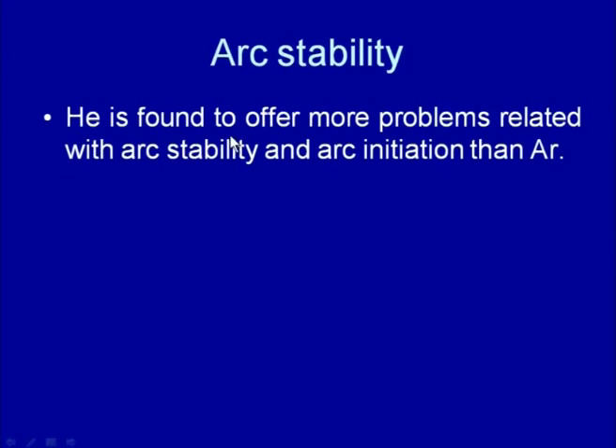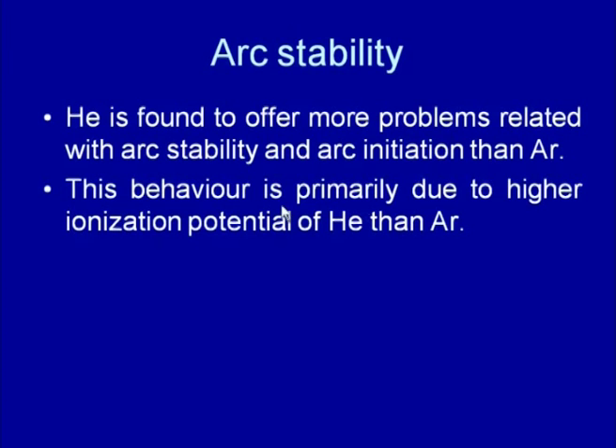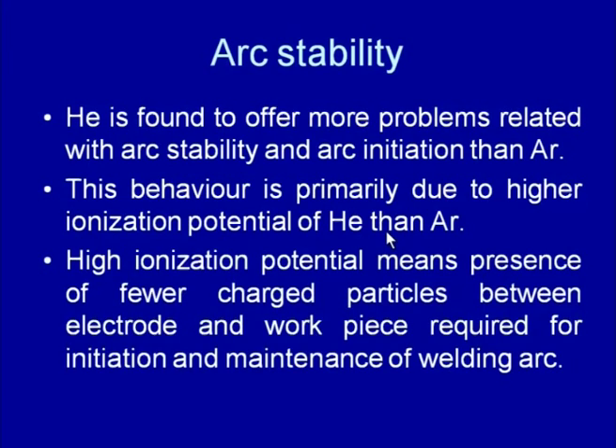Further, the selection of the shielding gas affects the stability of the arc. Helium is found to offer more problems related to arc stability and arc initiation than argon, and this problem is mainly attributed to the higher ionization potential of helium than argon, because higher ionization potential of helium means fewer charged particles it will be providing in the arc gap between the electrode and the workpiece, and the presence of fewer charged particles in the gap will result in difficulties in flow of current required for initiation and maintenance of the arc.